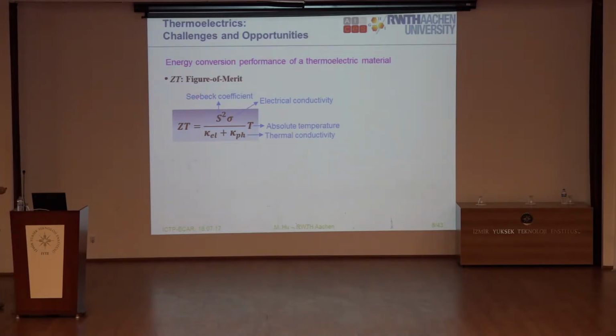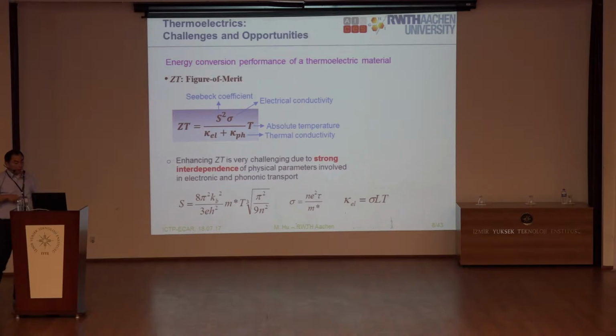So for example, the ZT coefficient is defined as the Seebeck coefficient squared and the electrical conductivity divided by the thermal transport property, and then times the absolute temperature. So although the formula is very simple, it's very challenging actually to enhance the ZT coefficient to be a very, very large value. This is because of two major parts, one is the electronic transport part and the other is the phononic transport part. Actually, they are strongly coupled with each other.